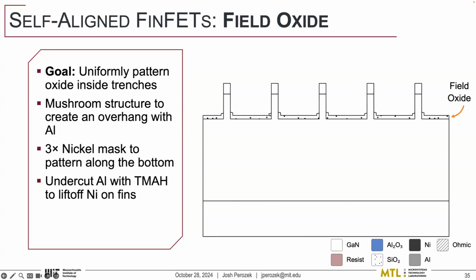So it's a little more convoluted than just etching back a single layer, but it's the only way that we've been able to find that you can actually repeatedly put this layer at the bottom of the fins without just destroying the gallium nitride with high intensity plasmas.